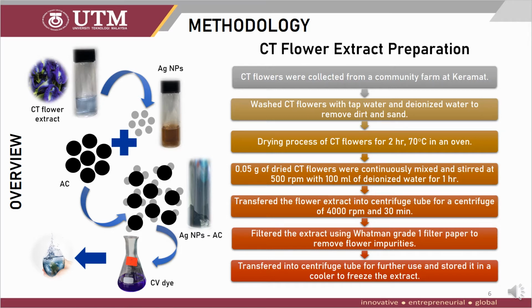First thing first is to prepare the Clitoria flower. First, collect the flowers, and then the flowers will be washed with tap water and deionized water, and after that the flowers will be dried for about 2 hours at 70 degrees C, and 0.05 gram of the dried flowers will be mixed with 100 ml of DI water to get the flower extract. After that, the flower extract will be centrifuged for about 30 minutes and filtered using filter paper to remove the flower impurities. And lastly, the flower extract will be transferred into a centrifuge tube for further use and stored in a cooler to freeze the extract.